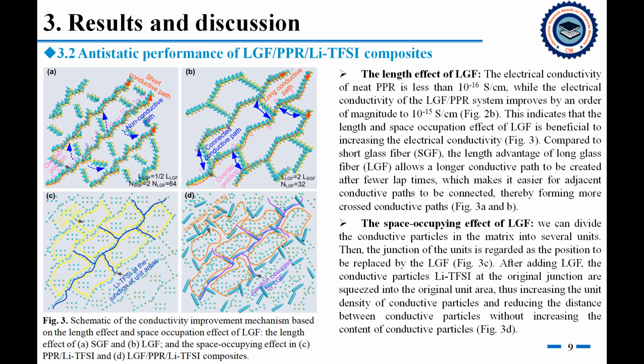Second, the space occupying effect of long glass fiber. We can divide the conductive particles in the matrix into several units. Then the junction of units is regarded as the position to be replaced by the long glass fiber. After adding long glass fiber, the conductive particles, organic salt, at the original junction are squeezed into the original unit area, thus increasing the unit density of conductive particles and reducing the distance between conductive particles without increasing the content of conductive particles.